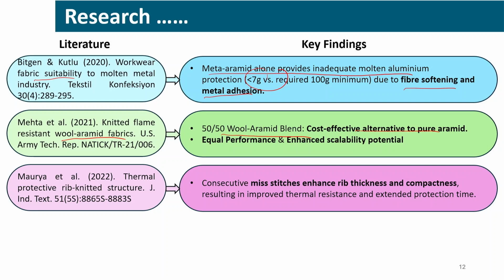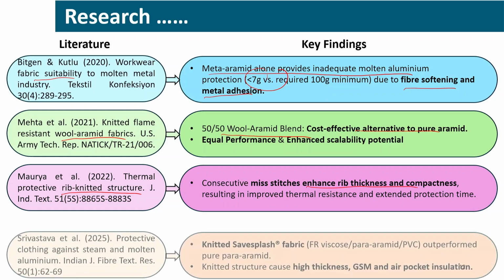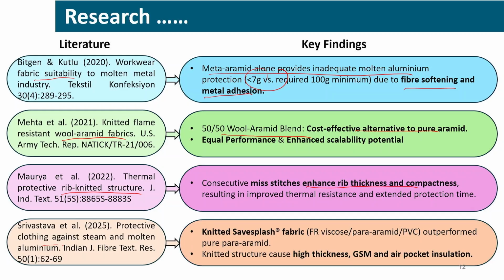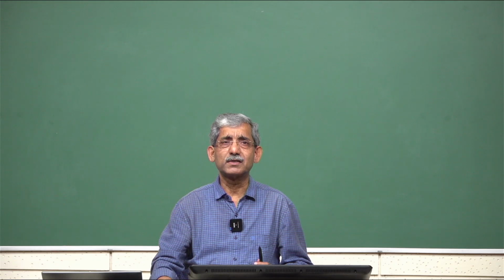Another study was on the thermal protective performance of rib knitted structure with different types of compactness. So, we found that there are different types of studies available. The latest study was on protective clothing against steam and molten aluminum, using a special fabric of FR viscose, para-aramid and PVC. They report that it outperforms pure para-aramid within their study limit, and the knitted structure gives high thickness, mass per unit area and air pocket insulation, which gives better thermal insulation against molten metal. So, these are a few research reports.